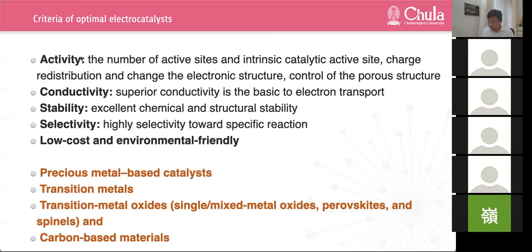The first one is activity. The catalytic activity is determined by the number of active sites and the intrinsic catalytic activity. Primarily, heteroatom doping of sulfur, nitrogen, oxygen, phosphorus, boron, and metal atoms, and defect control like edge and vacancy, will generate charge redistribution and change the electronic structure, which reduces the adsorption energy of oxygen-containing species on them and improves the intrinsic catalytic activity. Then control of porous structure, mesoporous, microporous, or macroporous, can also enhance the exposure number density of the active sites. The macroporous can give more mass transfer pathways, whereas the microporous can give larger specific surface area to increase the accessibility of reactants to the active center.